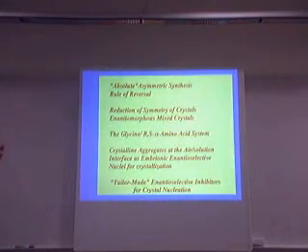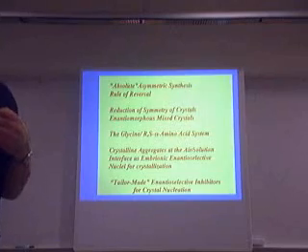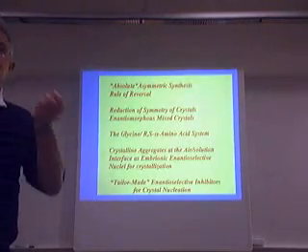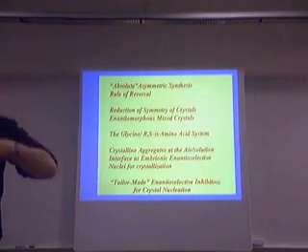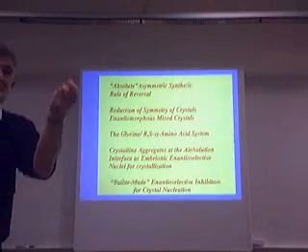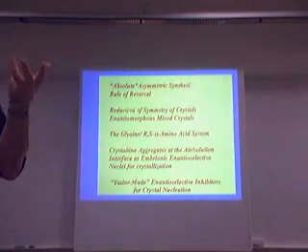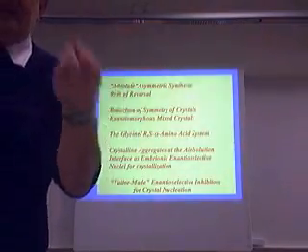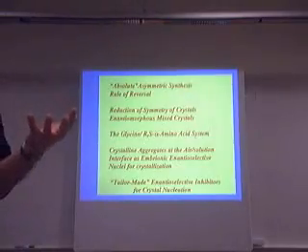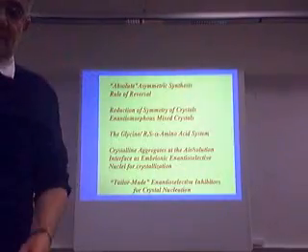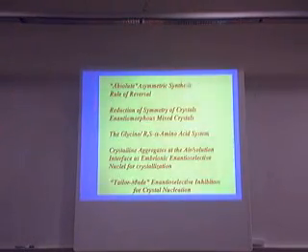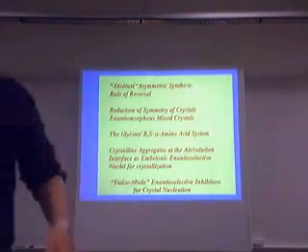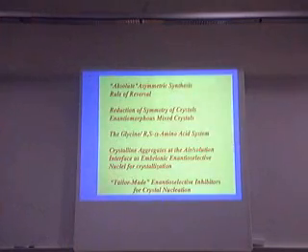I find this a very important extension: by investigating the mechanism of the formation of mixed crystals, we come to a very general concept, that a centrosymmetrical host can be converted into an enantiomorphous mixed crystal. And I shall show this by a kinetic control process. You can convert centrosymmetrical crystals into enantiomorphous crystals, and therefore we can extend the repertoire of crystals that we can use for mirror symmetry breaking also to the centrosymmetrical crystals. We shall see how important this is when we come back to the crystal of glycine.